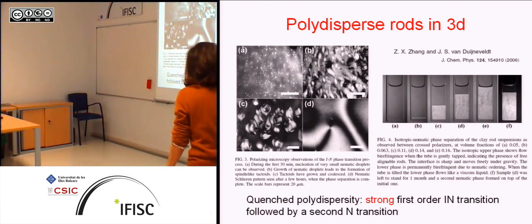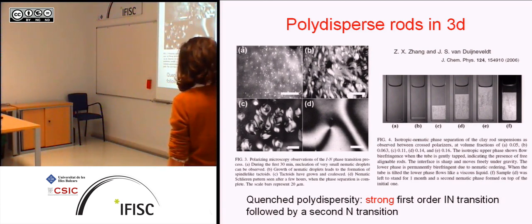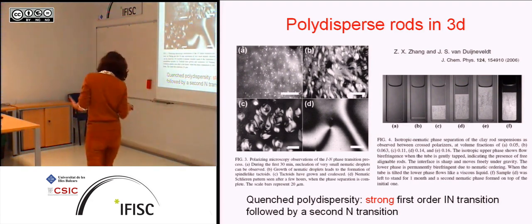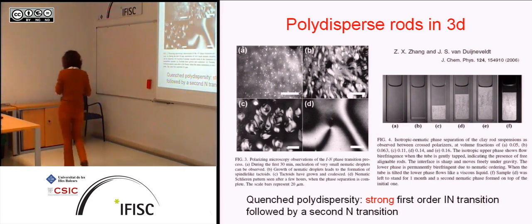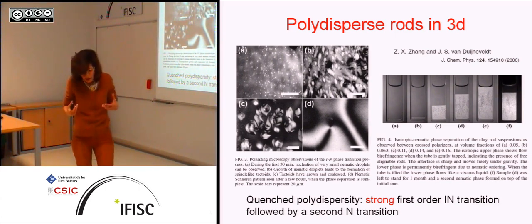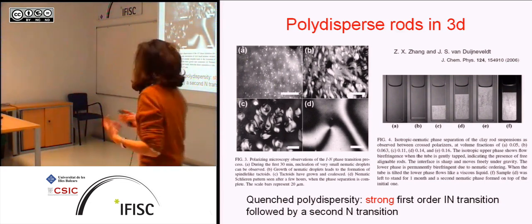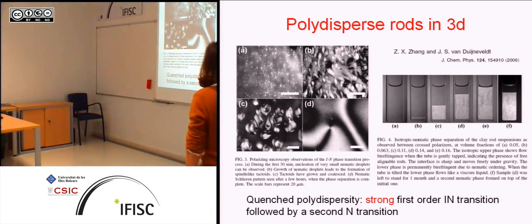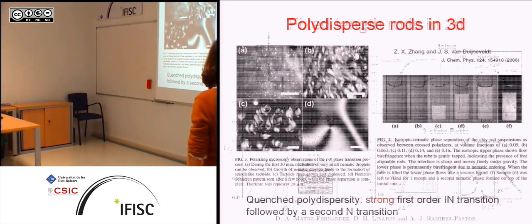If you look at these vials here, in this one, this is just nematic, and this is the isotropic. If you wait one month, I think that's what they say, there is a second nematic phase that appears, and this appears after a few hours. So clearly there are questions here that have to do with the fact that these things are long, they have time scales that you can control and study, but also they have more structure, and they can give rise to more diversity than the simple rods that Onsager treated in his very seminal paper.